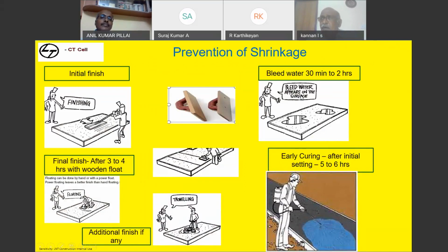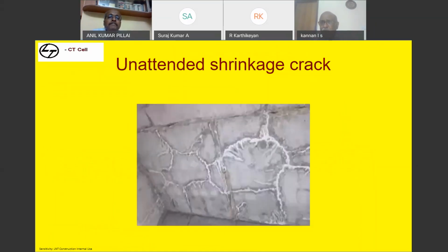Delayed finish: send the mason back after 3 to 4 hours, damp the entire surface, finish it off in a circular manner with the wooden float, and start early curing after 1 or 2 hours of the concrete, so that you are able to protect the entire surface of the concrete from shrinkage.